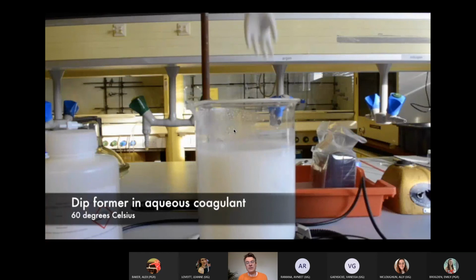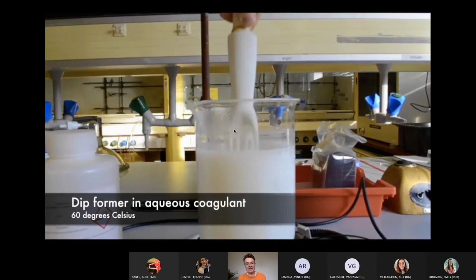So what you do is you get a ceramic mold, in this case a hand, and you dip it in a solution that contains a salt. Now, that salt then gets dried in an oven onto the ceramic glove. And what that salt does is that it really facilitates the latex particles to stick to that ceramic mold and really form a tight film of coagulated particles, like we saw in that little SEM picture before.